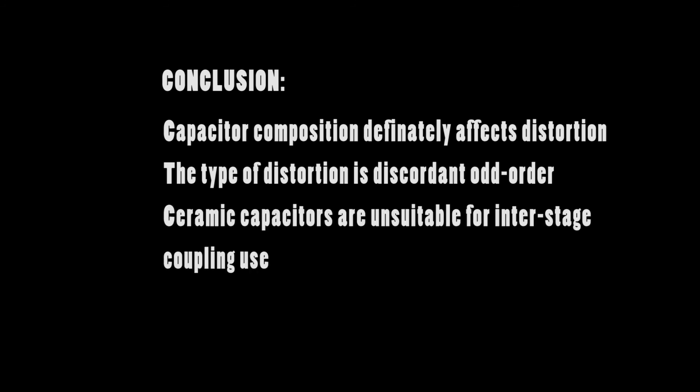So what conclusions can we draw? Capacitor composition definitely affects distortion. The type of distortion is discordant, and ceramic capacitors are unsuitable for interstage coupling.